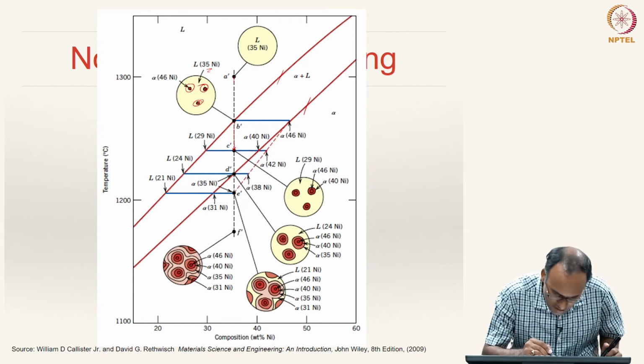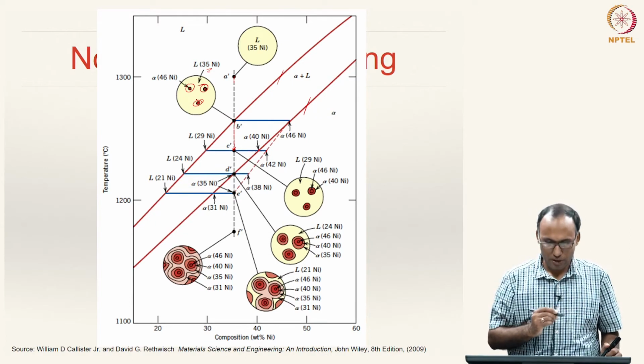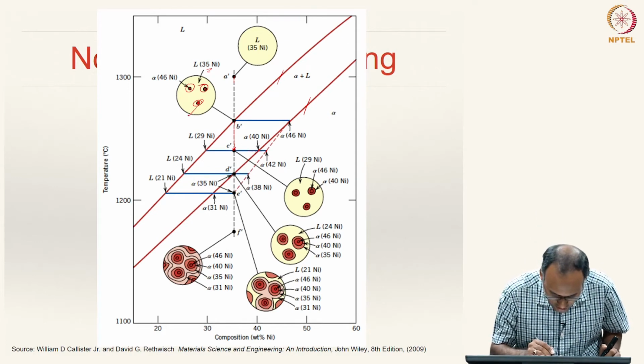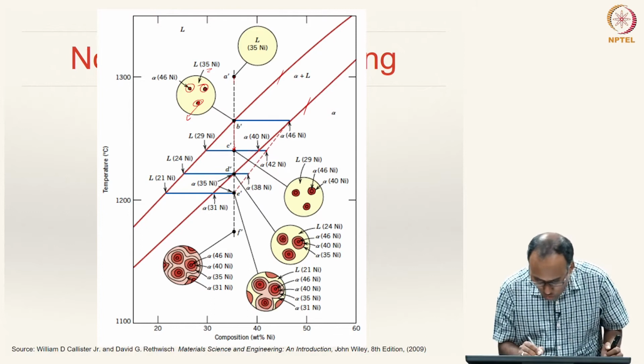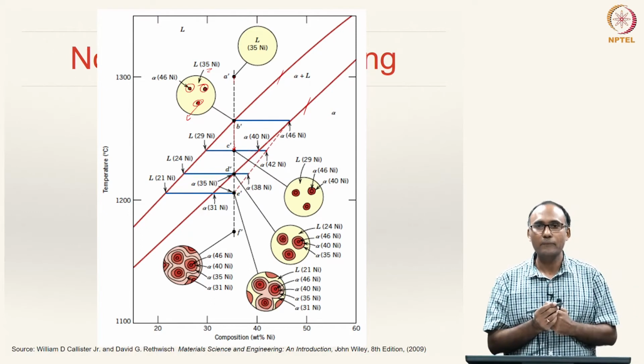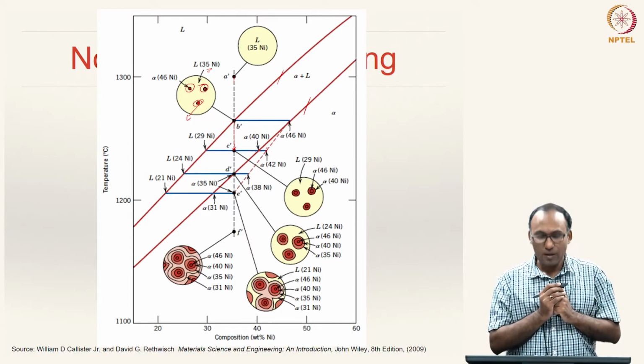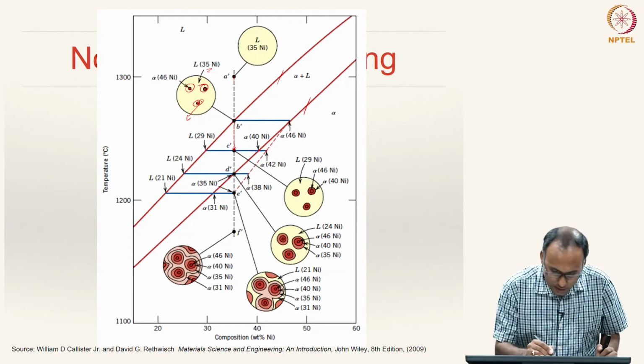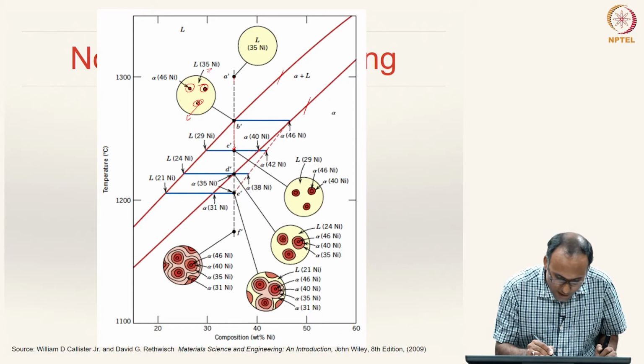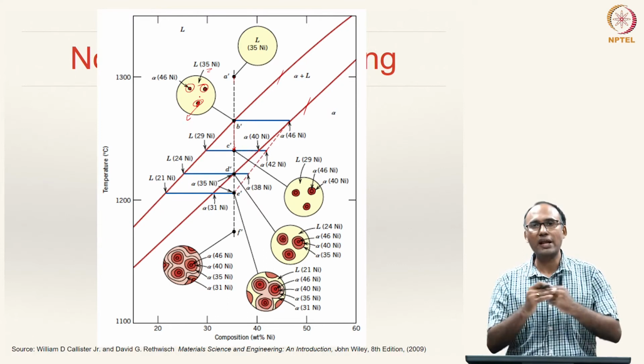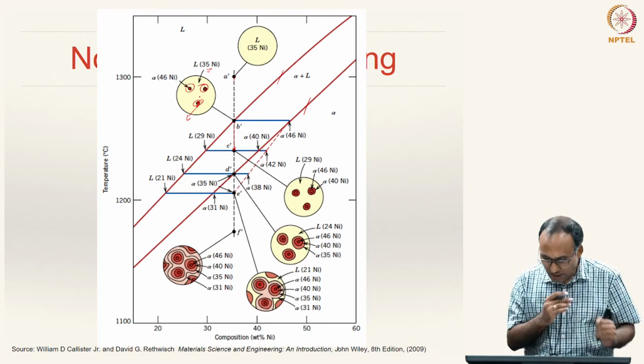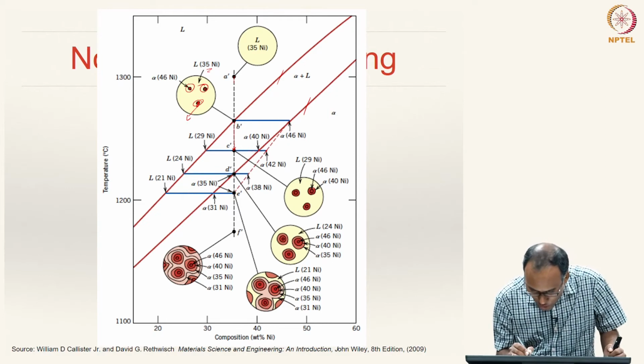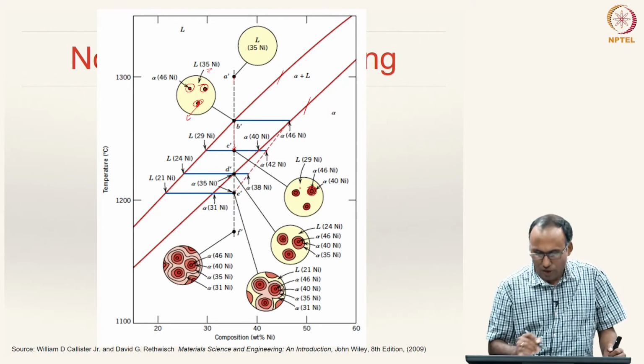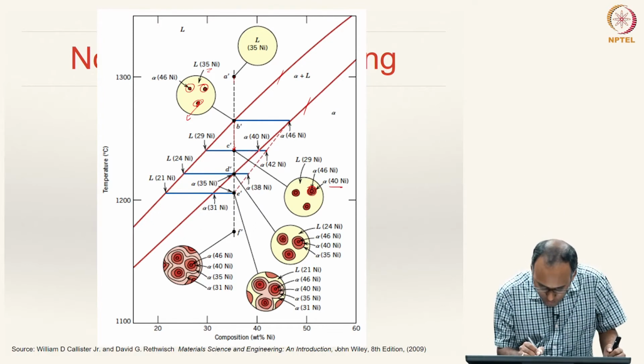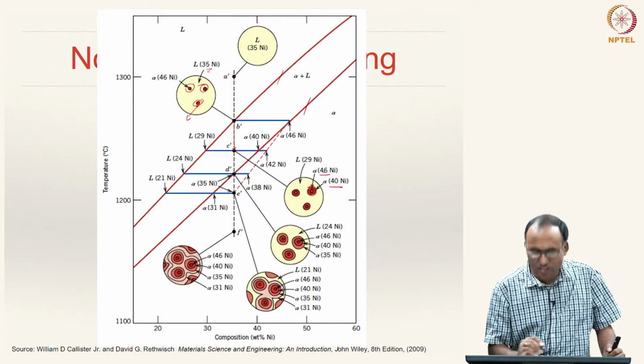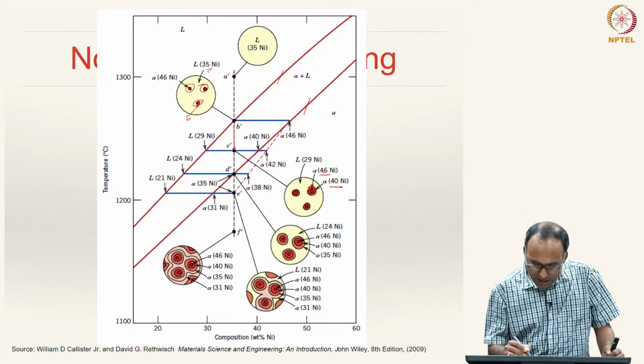What should happen? See, initially you have got 46% nickel formed here. By the time you come here, this 46% nickel should actually change to 40% or 42% in some sense, 42%, right. But if you do not give sufficient time, there is no possibility for diffusion to take place from the solid state to the neighboring liquid state or the neighboring solid that is there. And as a result, what happens is the outermost layer will have 40% nickel corresponding to this, and the innermost layer will have 46% nickel, giving rise to an average.